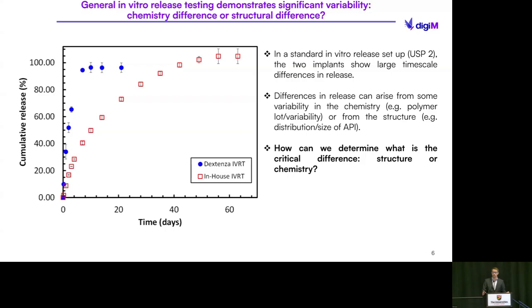But as we know, DEXTENZA swells. It swells out radially, so do those pores maintain themselves there? And also significantly, if it swells out radially and we're doing an omnidirectional in vitro release like this, the diffusion pathway is going to be dominated by diffusion along the radial axis of the implant here. Whereas inside the tear duct, it's very likely not going to diffuse along those ways because of the incredibly small amount of room it has to diffuse out through those sides. So that leads to the question of how can we determine what is the critical difference here? This structure, this chemistry, or potentially some other critical quality attribute?